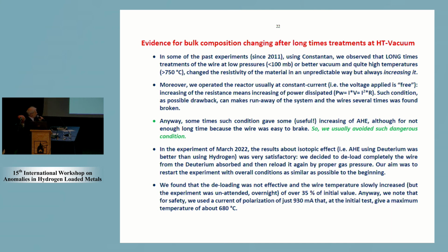The point is, because we work with constant current, if the resistance increases, the power increases, so the temperature of the wire increases. Usually, when we make the loading by vacuum, we watch to avoid too high a temperature. This time it seemed stable for 1 or 2 hours at the beginning, so we left the system overnight. But in the morning we saw the temperature had arrived at 860 degrees, starting from 680, so a very large increase.